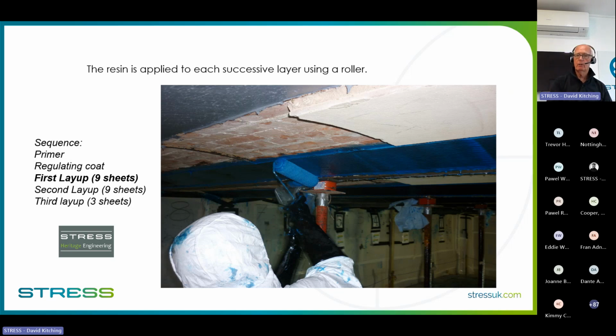And then you do the next, go down the line, do the next, and then come back and start doing second layup, and the same, and the third layup. And you can see here we use a roller. So the resin itself, we went for blue because we wanted to see exactly where it went. But in fact, normally it's a kind of a honey color. It's about the consistency of honey, and it rolls on, so it drips down your elbows all over the place, but will fully saturate the sheet. And that's what you want.